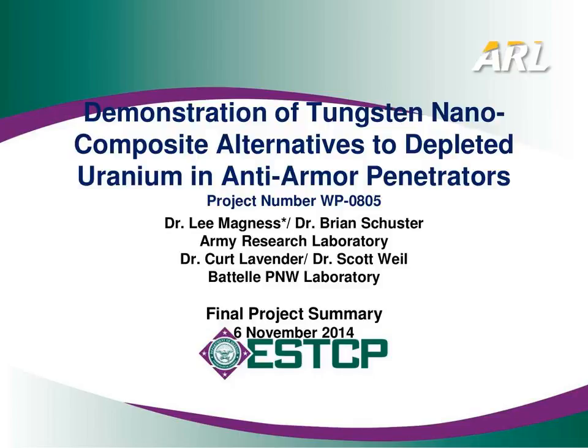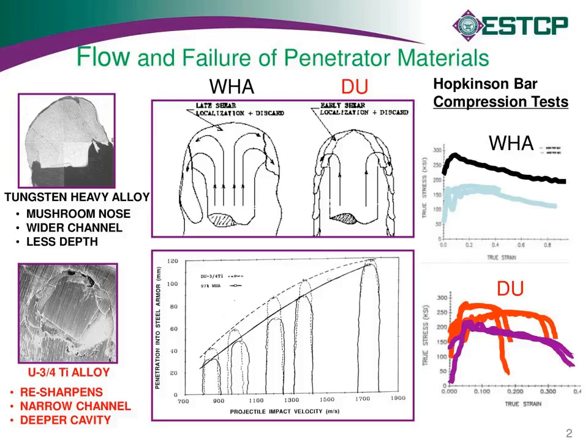If you go to the next slide, just some of the background. If you're familiar with the difference between depleted uranium and the other competing material that's out there right now for tank rounds and for kinetic energy rounds, it's basically the conventional tungsten heavy alloys, which are liquid phase sintered tungsten nickel iron or tungsten nickel cobalt alloys, and they basically fall short of the performance of depleted uranium by about 10% in penetration depth or 20% in terms of energy. It takes 20% more energy to get the same level of performance that you do with the DU projectile of an equal mass. The reason for that is shown in this slide.